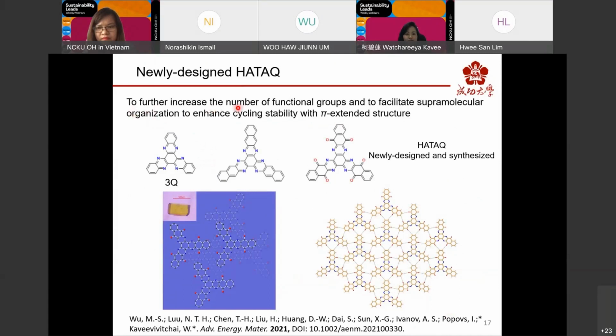So this work inspires us to further improve the performance. In order to increase the number of redox active functional groups, and also to facilitate supramolecular organization to enhance the cycling stability by using a highly extended structure, we have designed and synthesized a new compound called HATAQ with this structure. Compared to the 3Q, we use this compound here as an intermediate. You will notice that this compound now has 12 redox active sites capable of undergoing 12 electron transfer. And the molecules are packed together by hydrogen bonding to form layers like this and stacked together in a fashion similar to graphite.